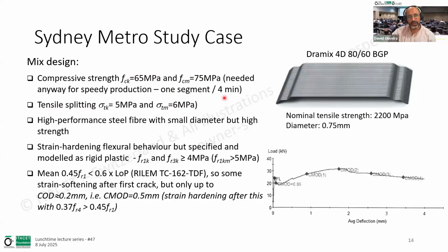And one thing we proposed was to change the steel fiber that was being used to a higher performance one, which we decided to adopt, the Dramix type fiber, 80/60, because it has a high tensile strength. It has a low diameter and would provide a good fiber network, a good amount of kilometers of fibers per cubic meter. And with that, we targeted and achieved a strain hardening flexural behavior, which would give us a very small direct tensile softening from the first cracking to the CMOD 1, the 0.5 millimeter crack mouth opening, which is more or less equivalent to a crack opening displacement. So one thing here is the crack mouth opening in flexure, and the other one is the crack opening displacement in direct tension.